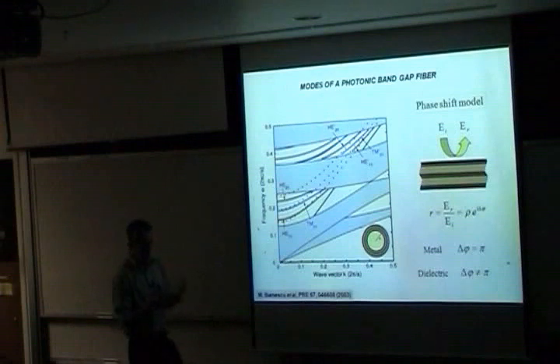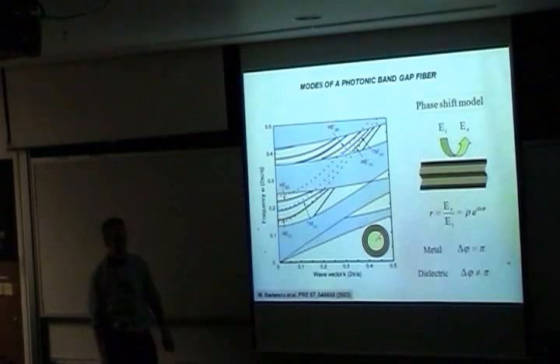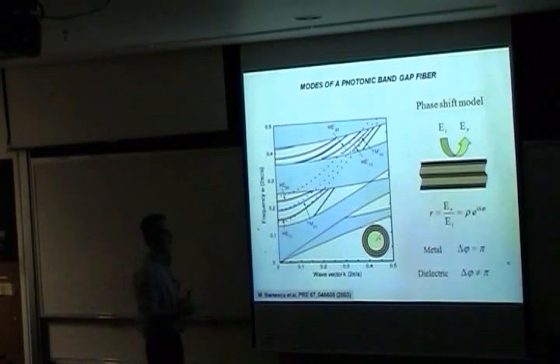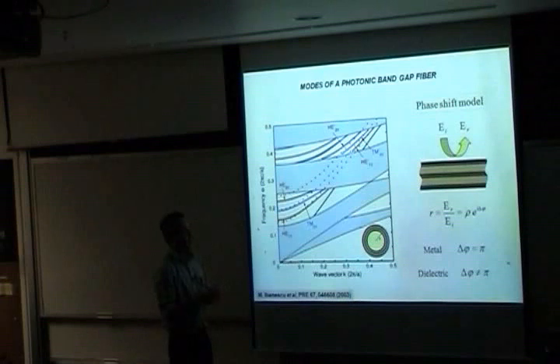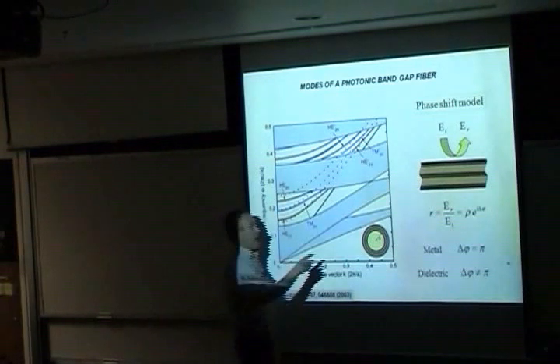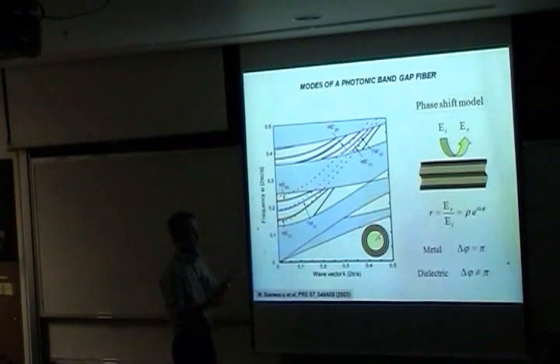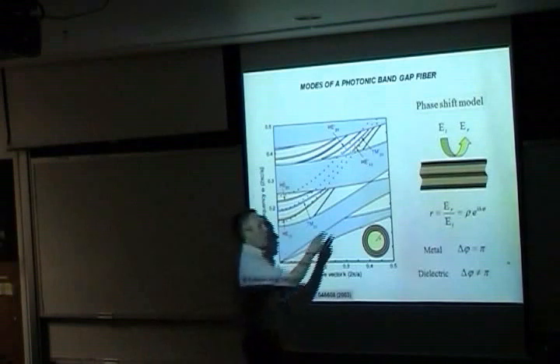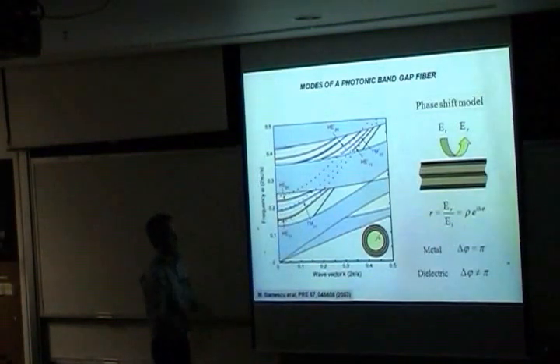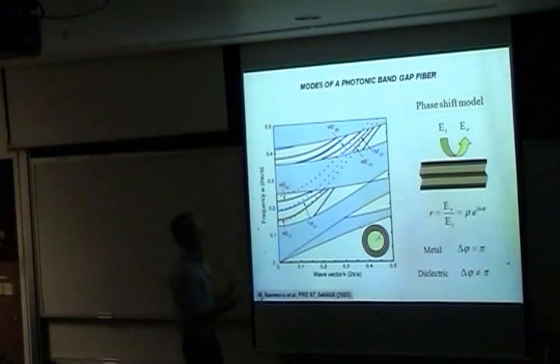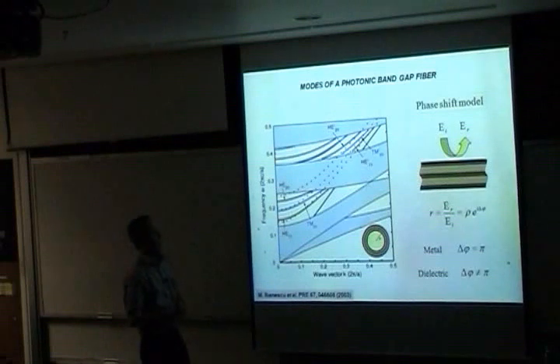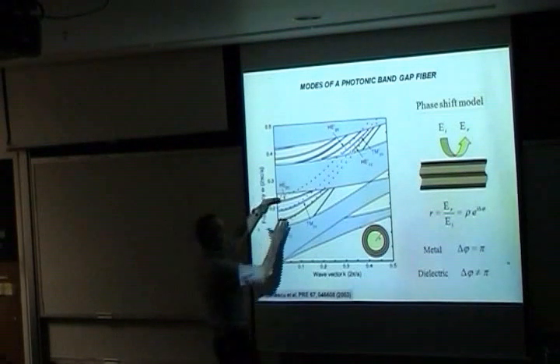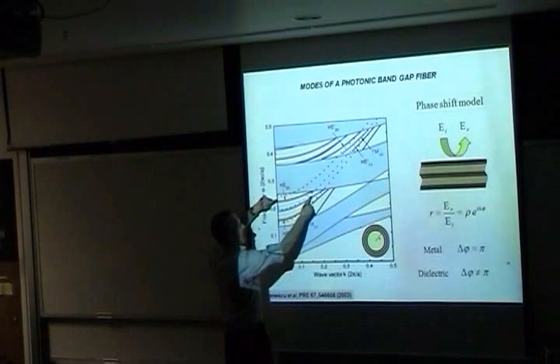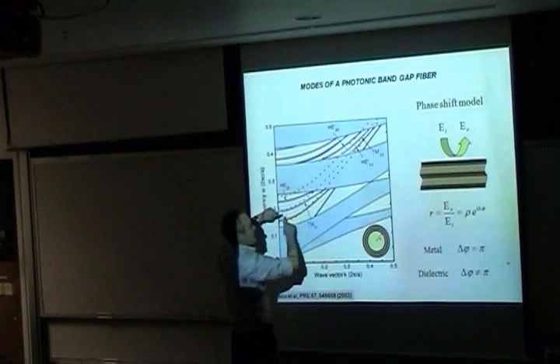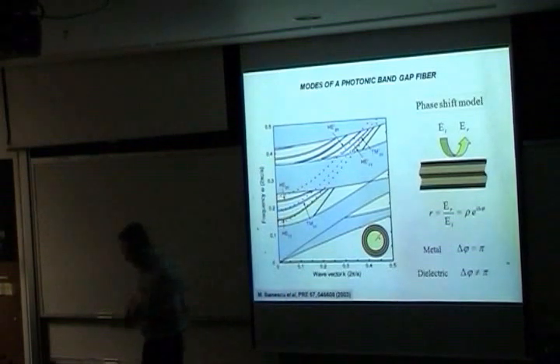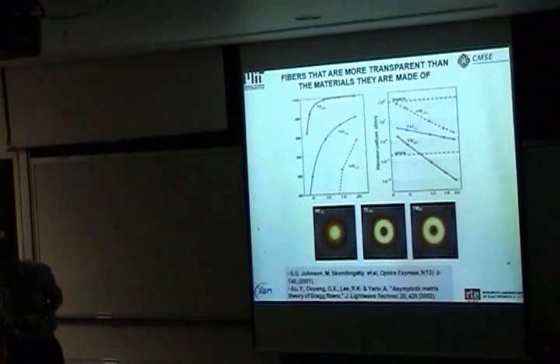One of them is that in the hollow metal waveguide, there's a pure separation into TE, transverse electric, and TM, transverse magnetic, modes. That does not exist in the dielectric structure unless it really is an angular momentum 0 type of mode, in which you actually get this very clear separation. Angular momentum 1 modes, and obviously angular momentum is a good quantum number here because of the cylindrical symmetry, give you mixed modes that have both the TM and TE nature to them. And basically the point of this graph is to say the modes here that we're looking at, these are the metallic modes. The ones in bold here are the modes that actually exist in the dielectric structure. And the point we're trying to make here is they're actually pretty similar and have some interesting and important differences.